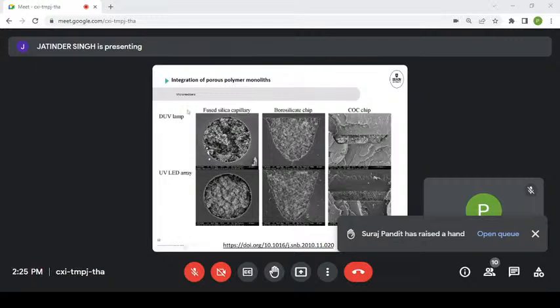Here we can see traditionally, using the expensive way, a deep UV lamp is used for the cross-linking of the polymer monoliths, which is irradiating light at 260 nanometers. All the chromatography-based people make these in capillary columns, and you get a picture that looks like that. Chemistry-wise, the surface of a borosilicate chip is actually the same as a fused silica capillary. So if you put a chip, fill that with a pre-polymerization mixture, you get exactly the same thing. And if you get a UV transparent polymer, and this was a special grade of COC, you can see that in a polymer chip, you can form the same monolith as well.